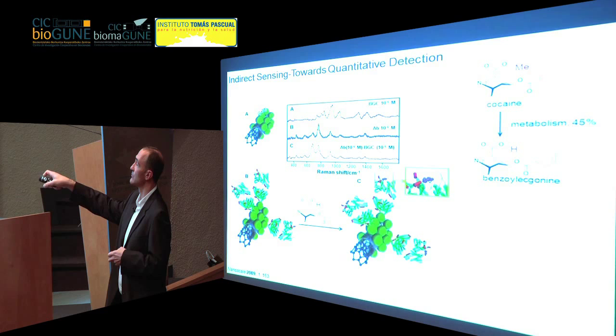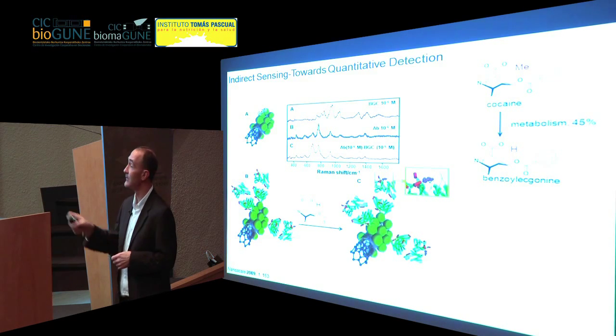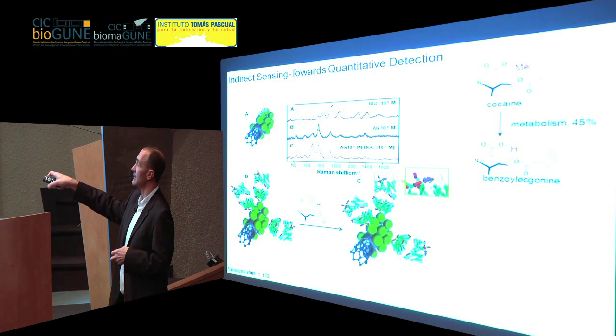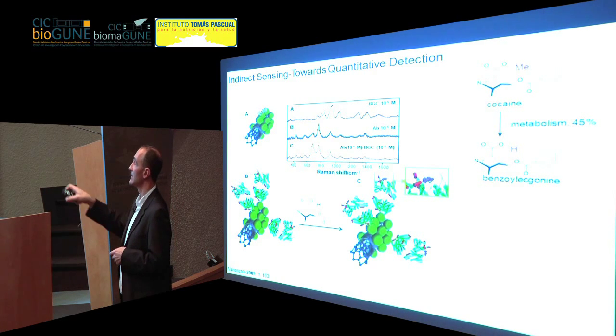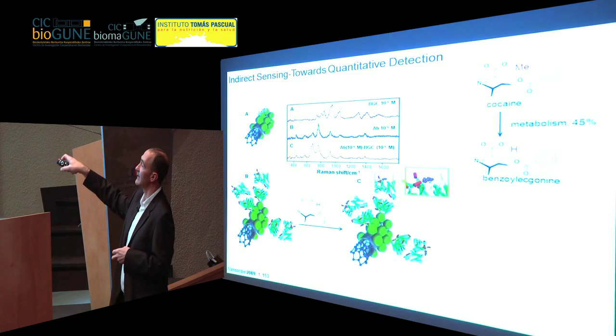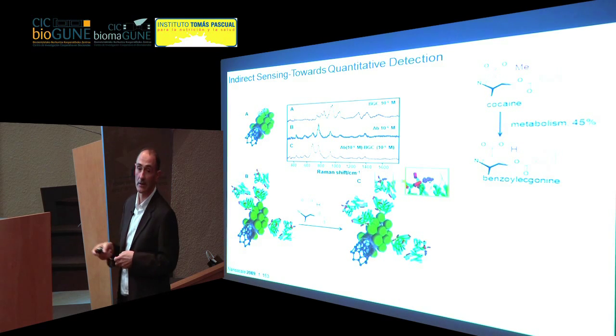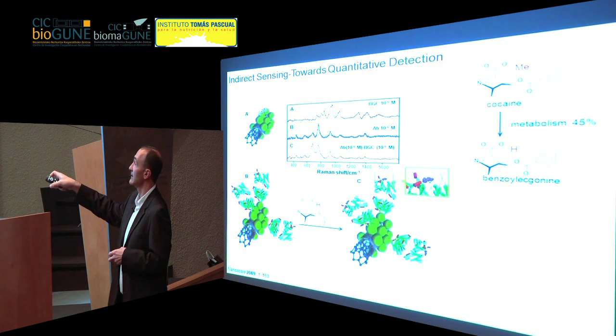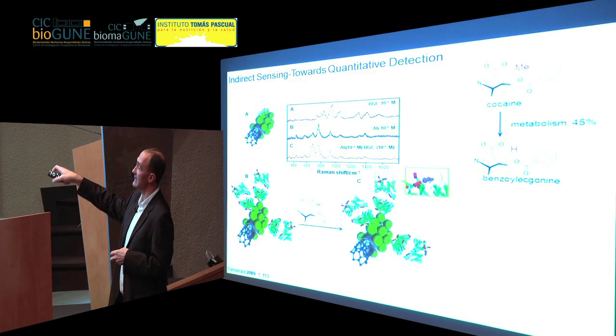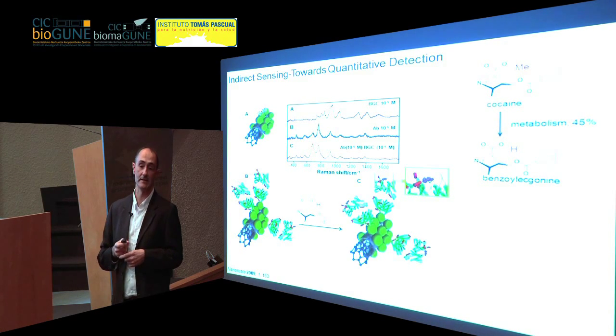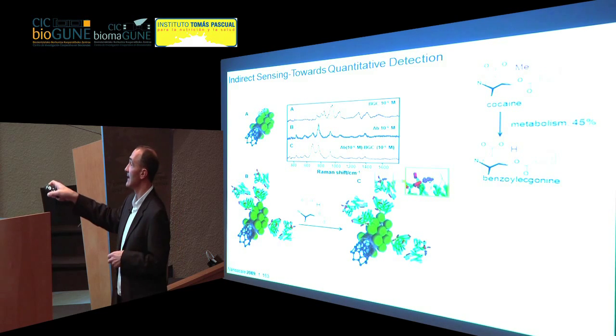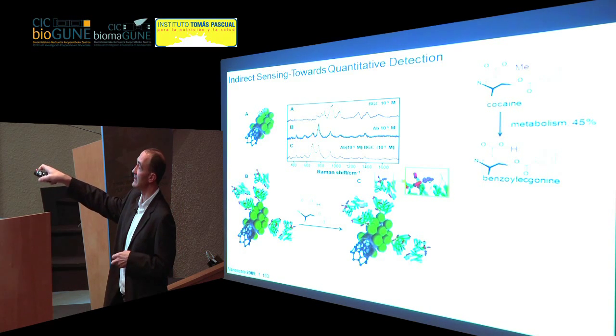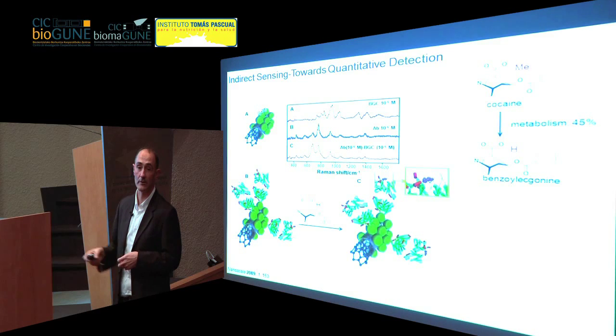So what we did was we found an antibody which is selective for benzoylecgonine. We attached the antibody to the metallic nanoparticles on the carbon nanotube. We were able to identify the SERS spectrum of the antibody alone. And then, when benzoylecgonine comes and binds to a specific place on the antibody, it changes some of the peaks that we found on the antibody alone.